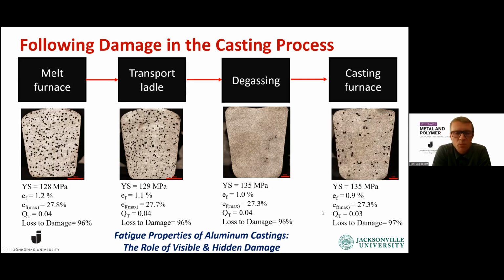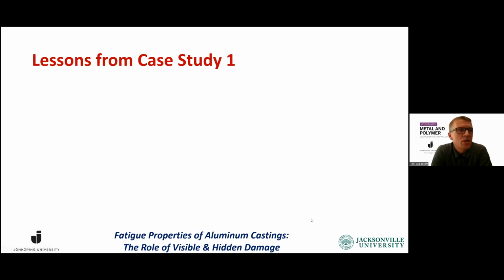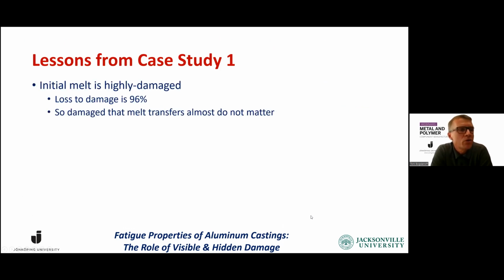And then we pour it one more time. What we see in this case is that all of this process is actually not changing anything. We can see a small degradation in the properties, but we have a loss to damage of about 96 to 97%. So the big question is, is it actually worth doing these steps when the quality of the melt is so low from the beginning?